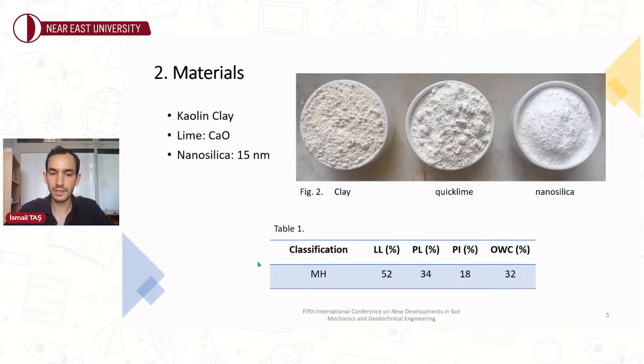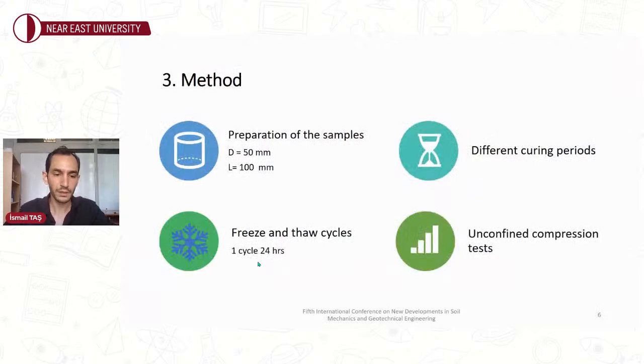The kaolin clay was classified as a high plasticity silty soil, MH, according to the standards. Also, the liquid limit of the soil was 52% and the plastic limit was 34%. The optimum water content of the soil was 32%. Quicklime was preferred as a stabilizing agent, and the nanosilica particles were 15 nanometers in size and have a purity of 99.5%.